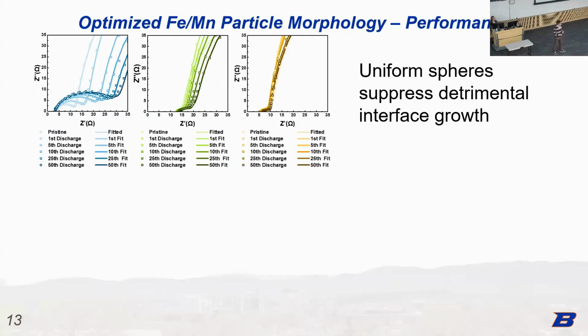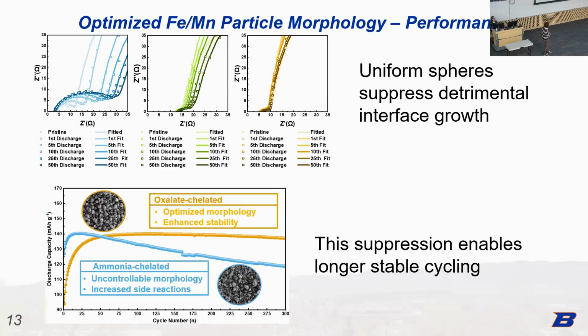And what that does is that with electrochemical impedance spectroscopy, which I won't explain right now, effectively the bigger the semicircle growth, the larger the growth of that interface that we do not like. As we can see with the ammonia chelated one, it gets a very big semicircle, which corresponds to a very big growth in that interface. And when that happens, the stability of our material is much worse because it blocks sodium from coming out. With the oxalate, it is able to suppress the growth of this interface and maintain a very high cycling stability.